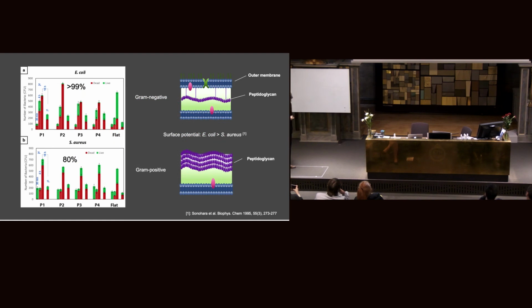So if we put all the results here between two different bacteria, gram-negative and gram-positive, we can find out the surface works much better on gram-negative bacteria. After 18 hours incubation, there's a huge difference between the pattern area and flat area. But Staphylococcus aureus, as a gram-positive bacteria, has a much lower death ratio.